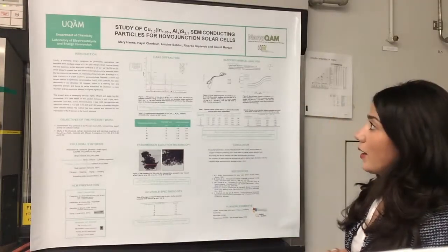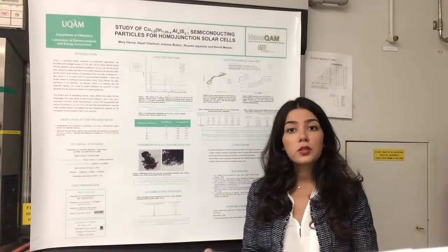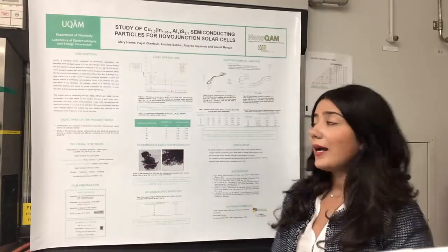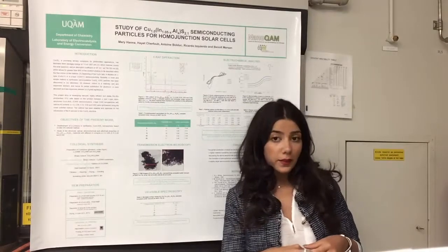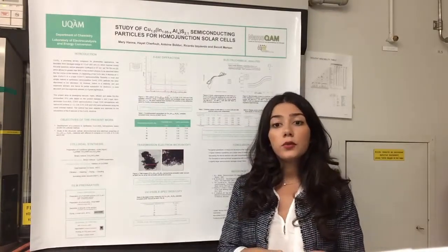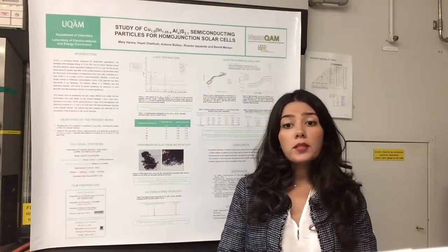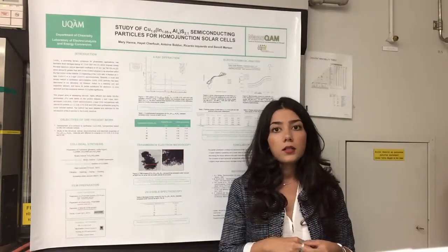It has a favorable bandgap energy value of 1.5 electron volts, which matches closely the solar spectrum. Plus, it has a high absorption coefficient of 10^5 cm^-1 that allows for greater than 99% of the incident photons to be absorbed within the first micron of the film. It's also possible to synthesize an N-type and a P-type semiconductor.